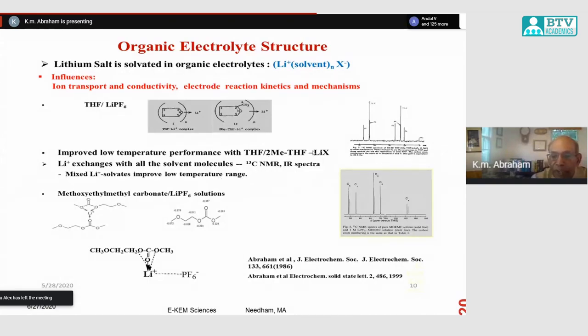And we also showed through some temperature-dependent NMR studies that these solvents are all exchanging with the lithium ion continuously, so that when you have a mixed solvent electrolyte, you have continuously exchanging solvents around the lithium ion. We found them to provide a better low temperature performance, for example. So structural studies of the electrolyte are very important in explaining this and also in coming up with new electrolytes for improved lithium-ion batteries.